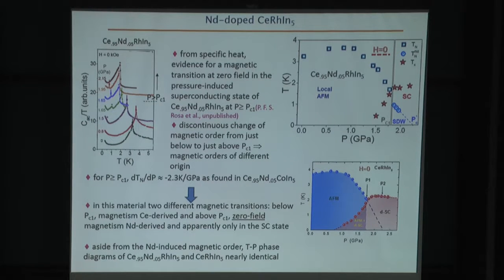So a logical idea was, what happens if you add 5% neodymium to cerium rhodium indium-5? This is a problem that Priscilla Rosa has been studying, and she's used AC heat capacity measurements to look at this. Her data are summarized in this panel here. This sharp peak in the AC heat capacity at low pressures is just the antiferromagnetism.